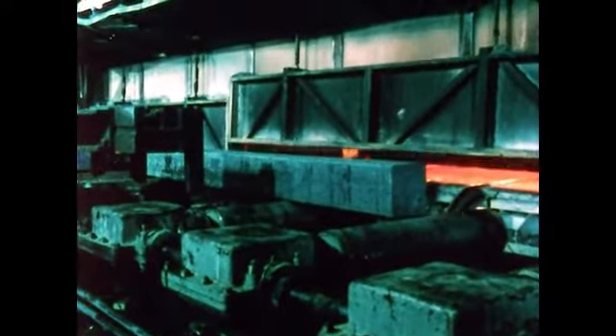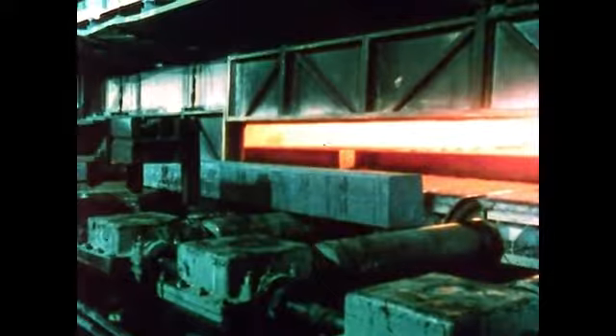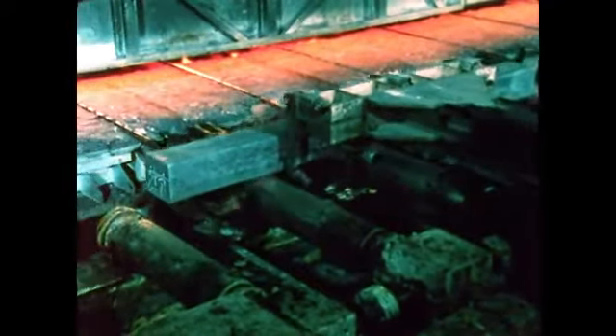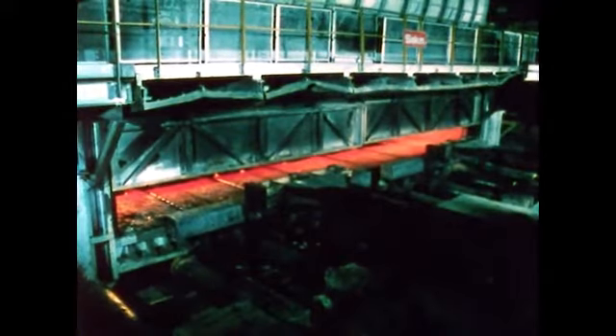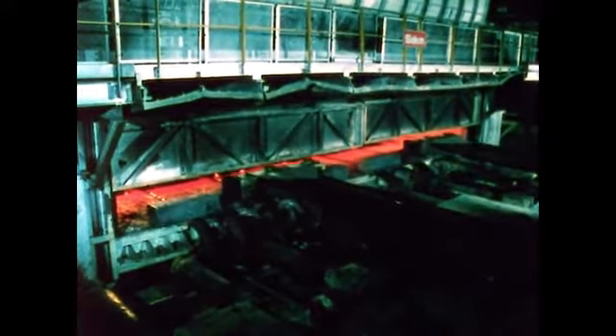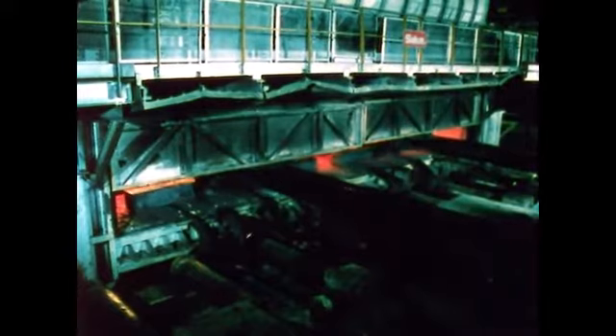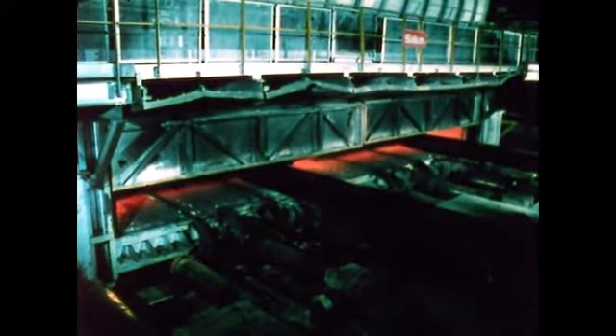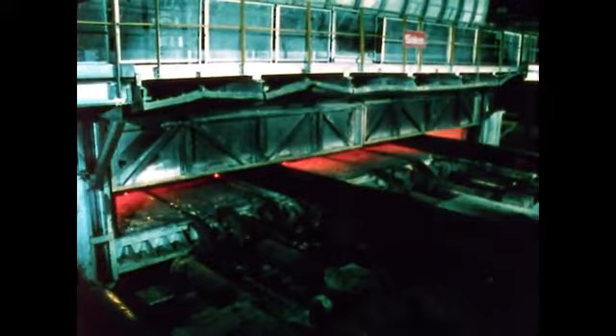This bloom from our continuous caster is about to start its journey through the world's first totally computer-controlled precision rail rolling and straightening line. By the time it reaches the end of the rail mill, this 15-foot-long bloom will have become four 39-foot or two 78-foot lengths of the finest, most modern rail ever produced. The bloom is first charged into this 3-zone reheating furnace, where it will be brought up to a temperature required for hot rolling.